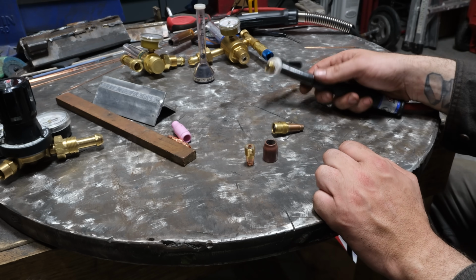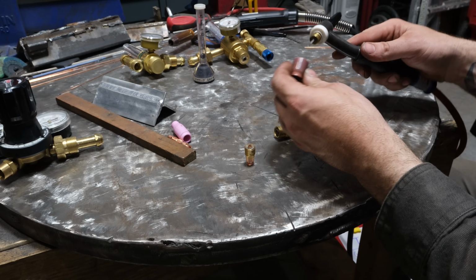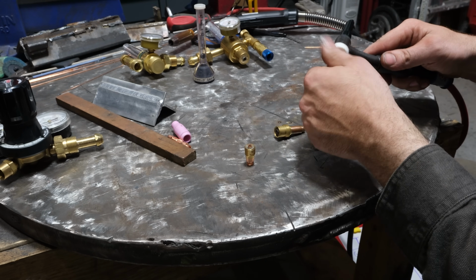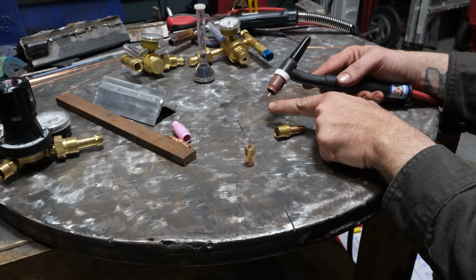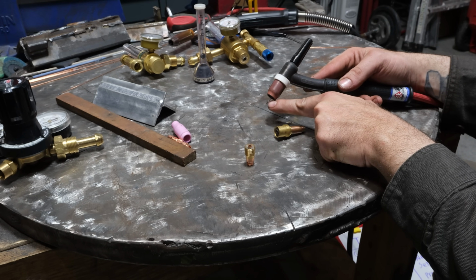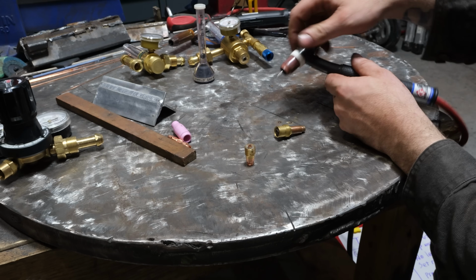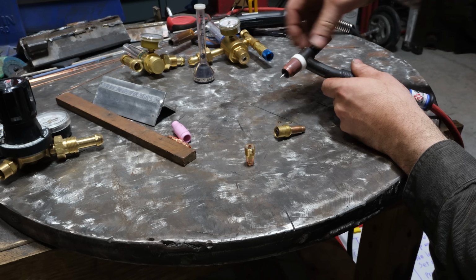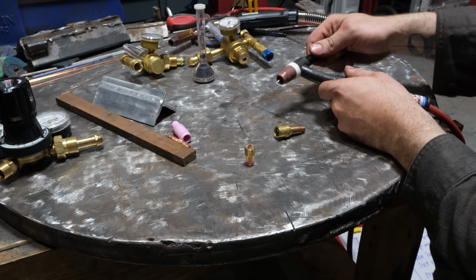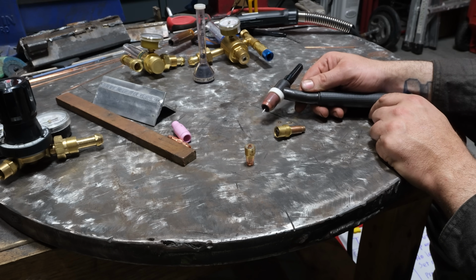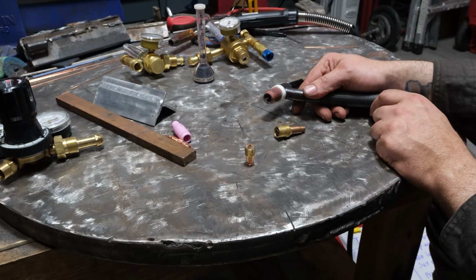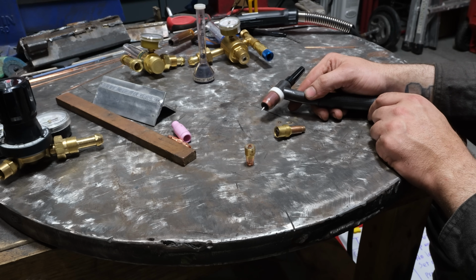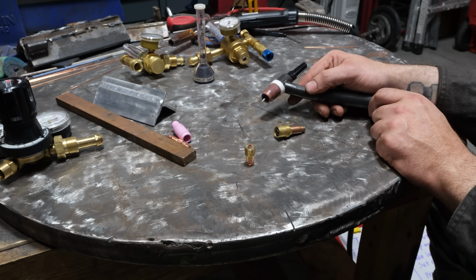Now your stick out obviously matters. If your stick out is a mile outside of the cup, even with a gas lens, you're going to have to run more shielding gas. If you put that in there quite a ways and you're able to weld with it barely sticking out, guess what? You can cut back your gas flow down to 10, 9, somewhere in there cubic feet an hour at 120 amps. So stick out matters hugely.